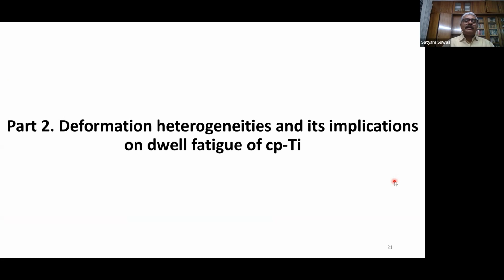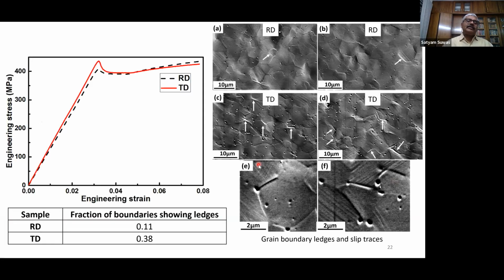Now, in the second part of this presentation, I am going to deal with deformation heterogeneities and how they affect the dwell fatigue of titanium. Now, this is a stress strain curve. This is repeated here for this material, and here we did some kind of slip trace analysis for both these materials, tested along rolling and transverse direction.